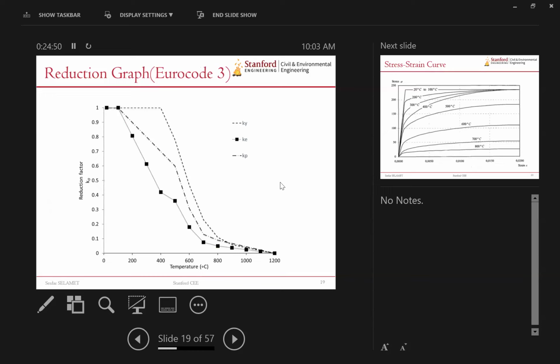So we have KE that represents the reduction factor for elastic stiffness. You can see that up to 100 degrees, everything behaves as it does at ambient temperature. After 100 degrees, the stiffness will drop significantly up to 400 degrees, and then it will vary and reach almost zero at around this temperature. So we're basically saying at around 1000 degrees or so, we don't have any stiffness left in the steel, so we cannot really solve a numerical problem after that. We have to make sure that we are bound to 1000 degrees or so. But the yield stress will stay pretty much the same until 400 degrees. Up to 400 degrees, the strength design that you do will remain exactly the same for fire conditions. So this is a good thing. But after that, it also starts its reduction all the way to zero when it reaches 1000 degrees.